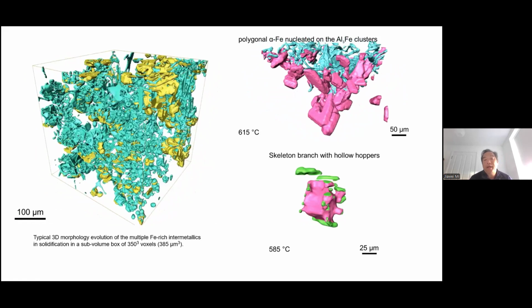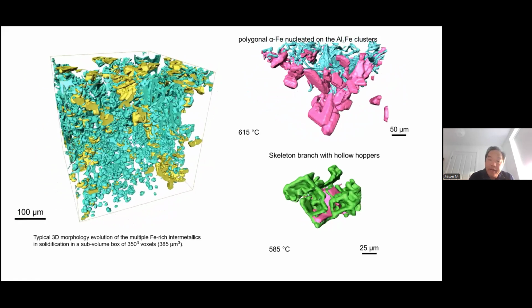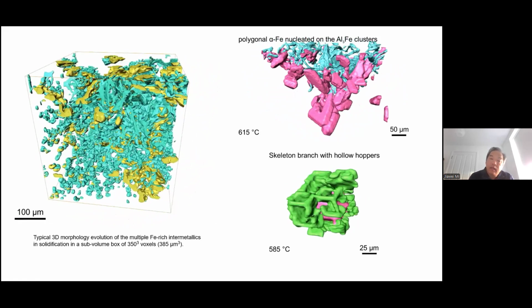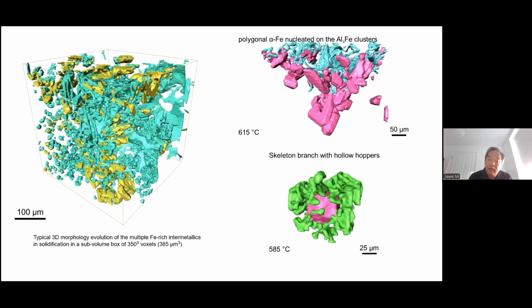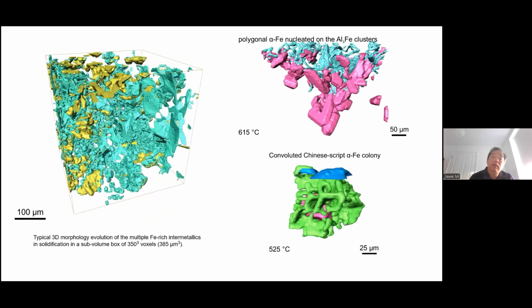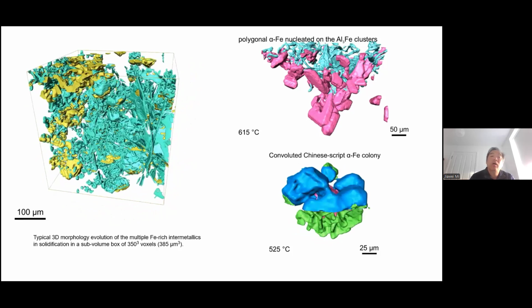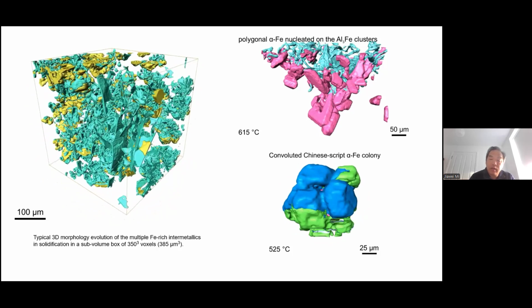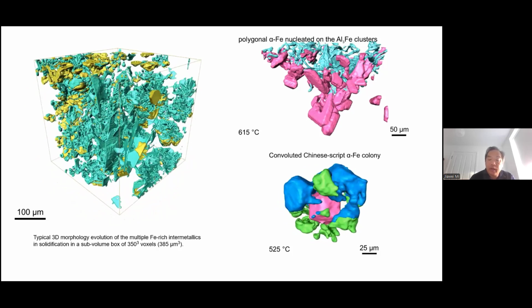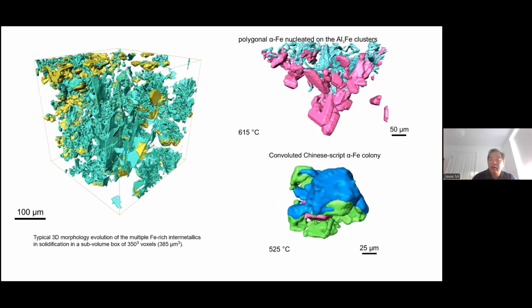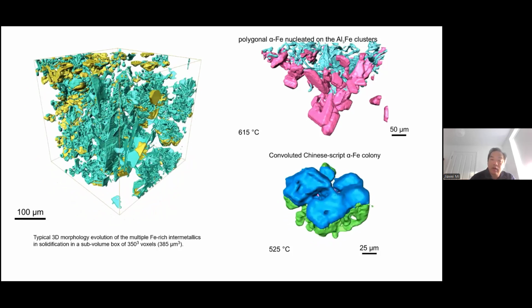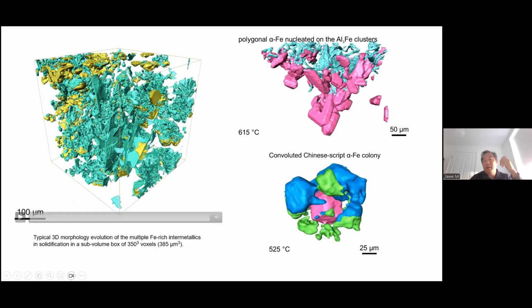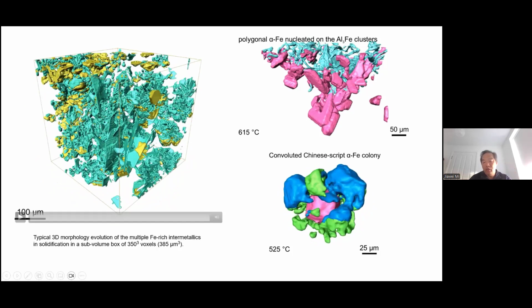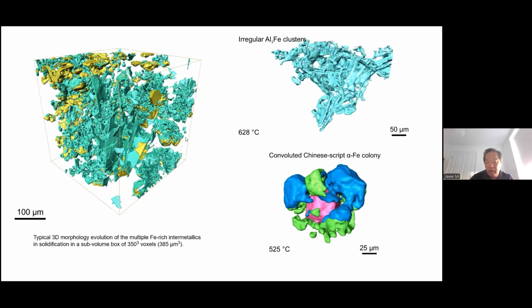Now we need to find a way to control this formation. And because these phases were formed in the solidification process, we need to apply some kind of control in this solidification process. So what kind of actual control can we do? In my research group, I have done a lot of ultrasound-based methods, which apply ultrasonic waves into the solidifying melt, or pulsed magnetic field. So I'll give you some examples here.